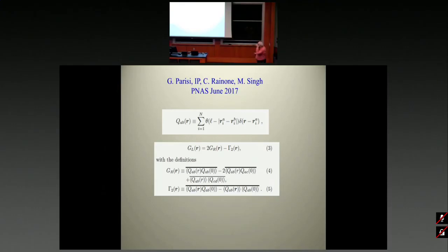I'm not going to bother you a lot. Just as an example, the gamma 2 is a simple second-order correlation function of the overlap function Q minus the mean of Q. This is a slightly different one, which has A and B and A and C and C and D, so more replica are involved. Let me point out that these look to the eye as 2-point correlation functions. In fact, they're 4-point correlation functions, because already the overlap function itself has 2 particles involved. None of the interesting phenomena in disordered systems are apparent with 2-point correlation functions. I'm saying this in parentheses. You always have to go to 4th order or higher.